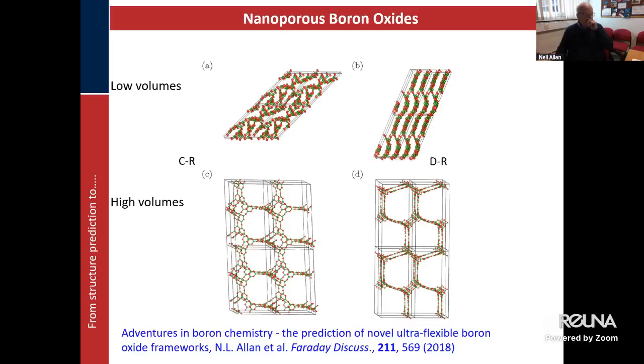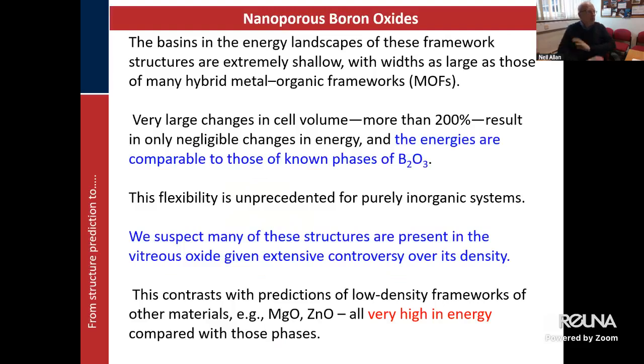But one of the crucial things that we predicted is that these were low in energy. They were about the same energy as the known solid state phases of boron oxide, alpha B2O3 and beta B2O3. And people have predicted nanoforms for all sorts of oxides, including zinc oxide, but they're all massively high in energy. It would be very difficult to form.